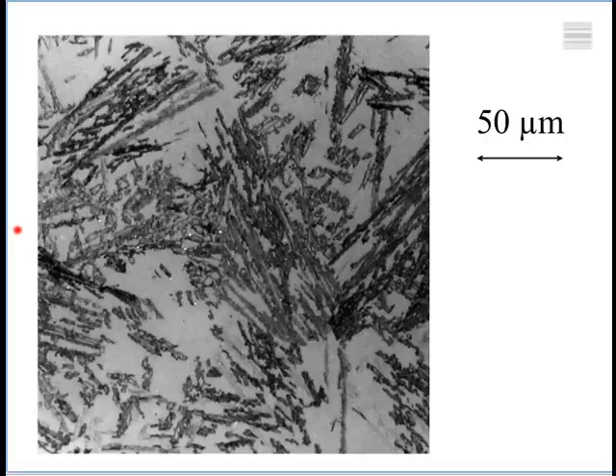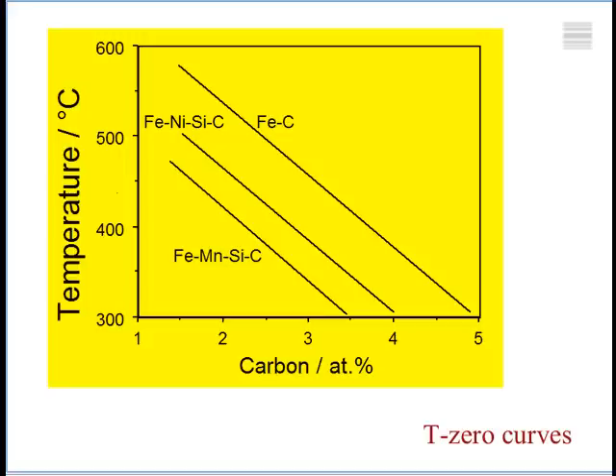So with that particular steel, I have the problem that there are large amounts of austenite which are mechanically unstable and transform into large regions of brittle martensite, and we get poor toughness. So even though this microstructure is very fine, this is not. Okay? And that's like putting a brick into the microstructure, which is the size of 50 micrometers. That's no good. Now, one way is if I reduce the average carbon concentration to 0.2, and the other way is if I can, by alloying, shift the T0 curve to larger concentrations. So this is the bad steel, and this is the T0 curve by substituting nickel for manganese.